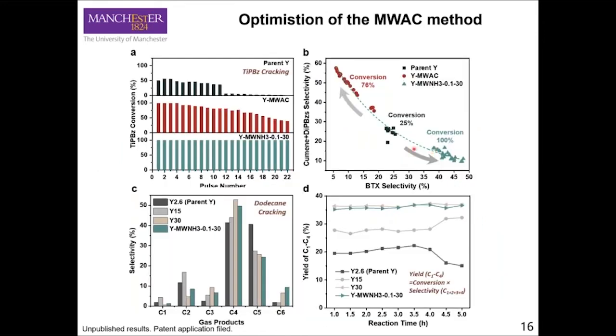So as you can see over here, we can also produce the hierarchical zeolites using these simplified methods. We also found that this method is quite interesting because by playing with the process parameters, we are able to direct the selectivities of the cracking process. We're still investigating this aspect, and the work hasn't been published yet. These are some preliminary results.